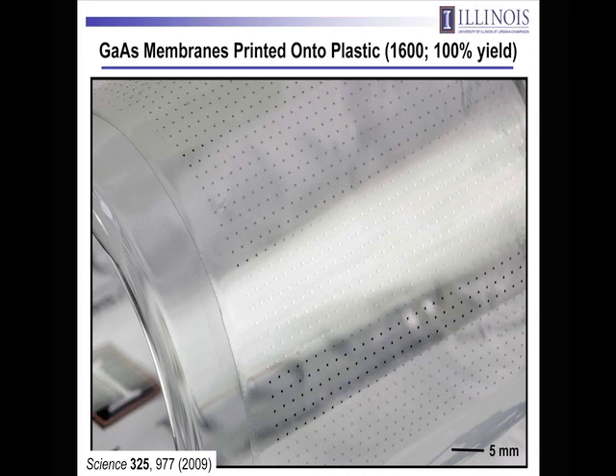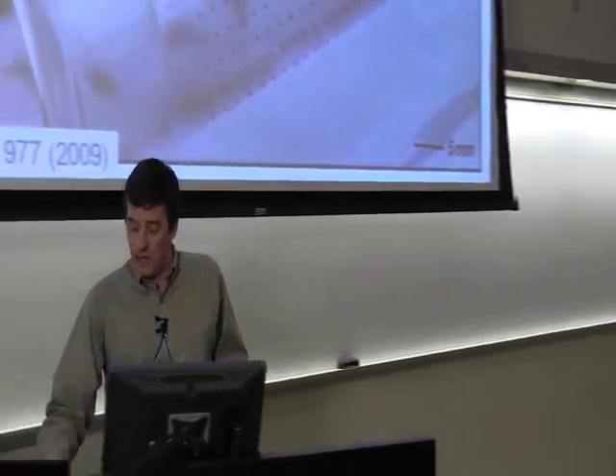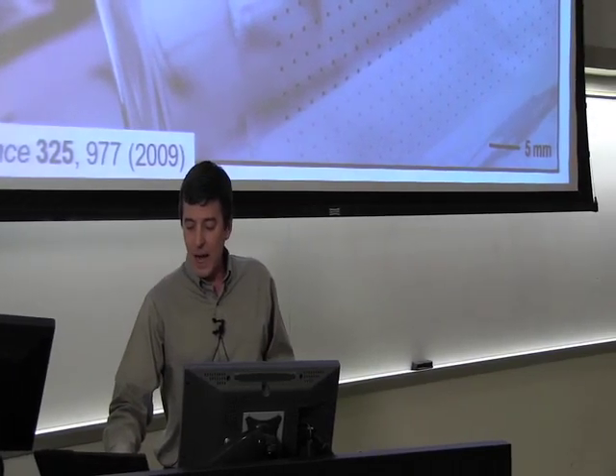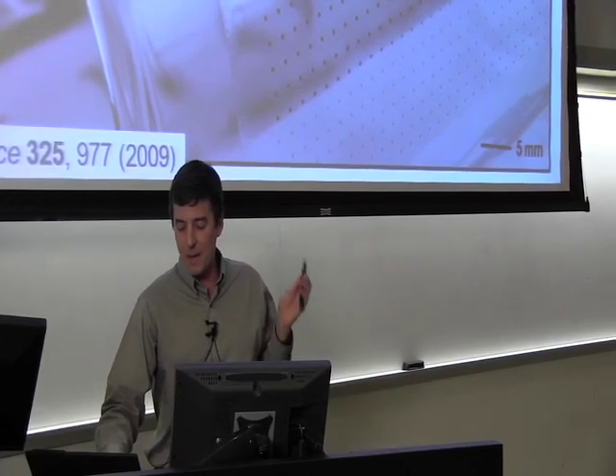So that was done on a flat sheet geometry, and then subsequently just wrapped it around this cylindrical glass support to just show the mechanical flexibility here, which is deriving from two things in this case: the thin geometry of the gallium arsenide nanomembranes and the small thickness of the underlying plastic substrate. That favorable adhesion mechanics, which results from the thin geometry of the gallium arsenide, allows these things to stick and stay adhered even when bent.